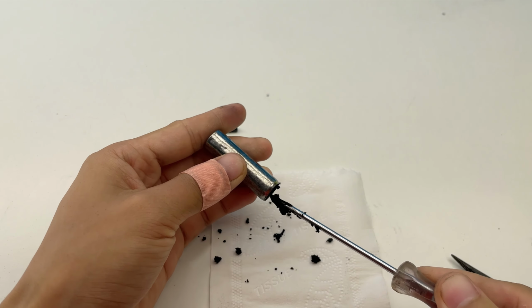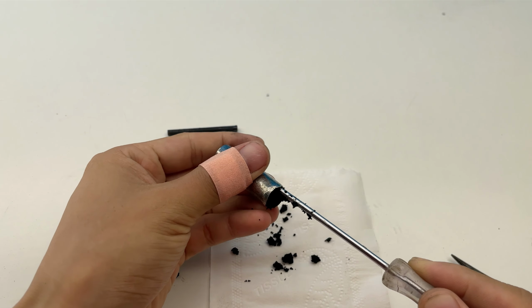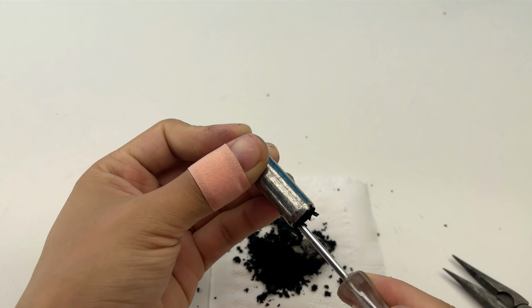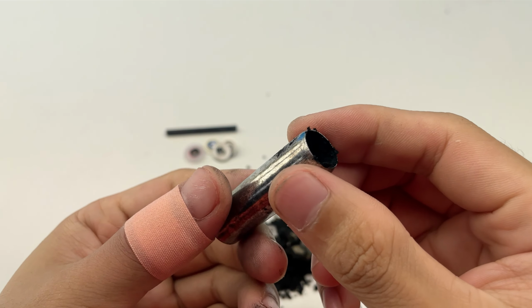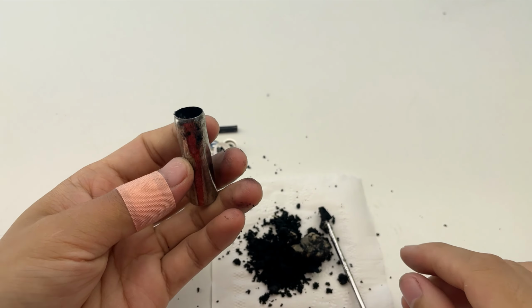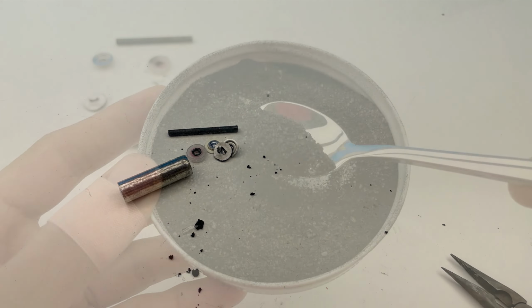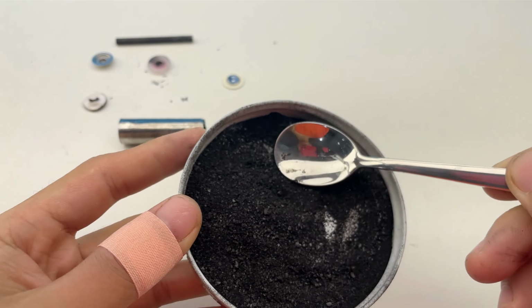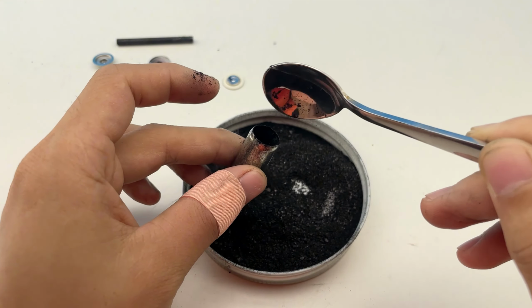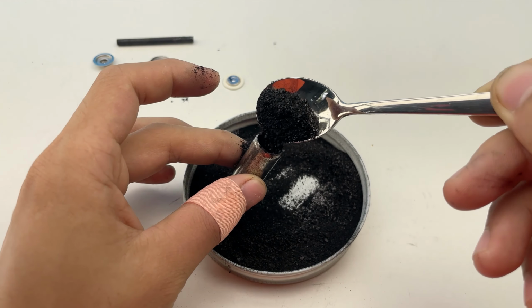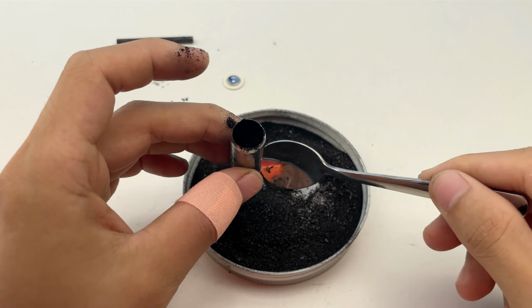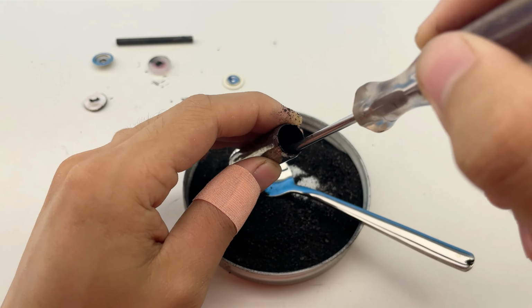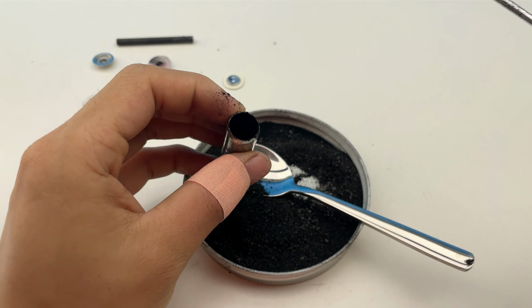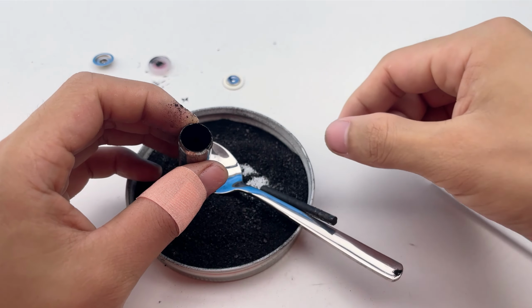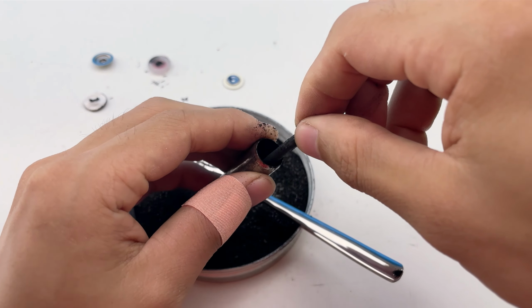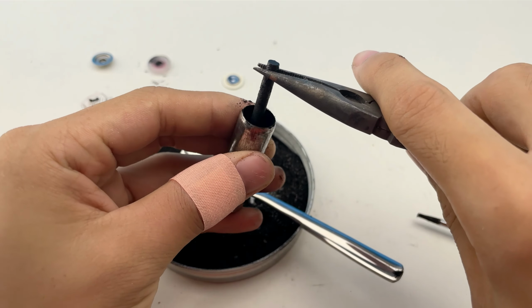I took out all of that carbon to prepare for the next step. Slowly, I poured the prepared salt and charcoal mixture back into the battery casing. In a typical battery, when energy is depleted, it's mainly because the electrolyte dries out or the chemical reaction is interrupted. When the new mixture is added, the salt reacts with moisture to form a fresh electrolyte, while the charcoal powder helps electrons move between regions that can still react. As a result, zinc that hasn't been fully oxidized can be reactivated.